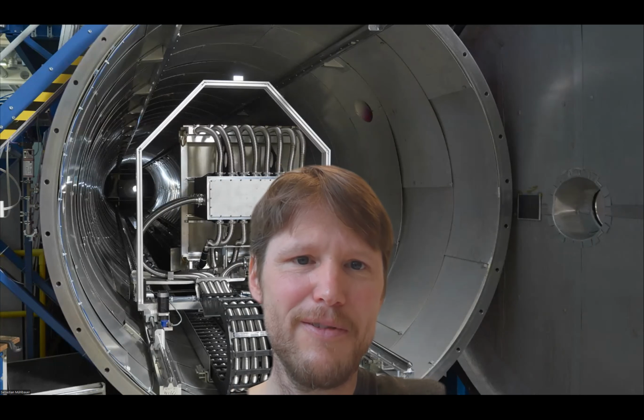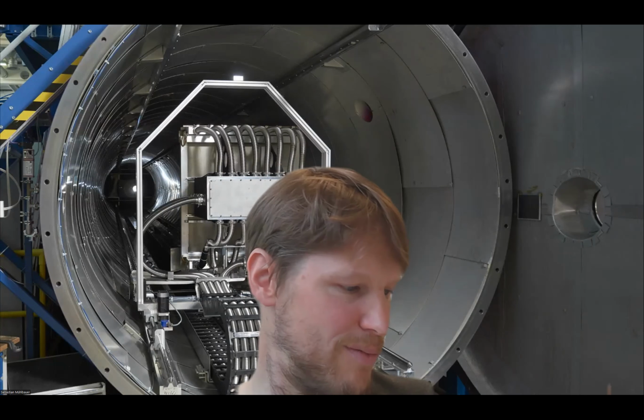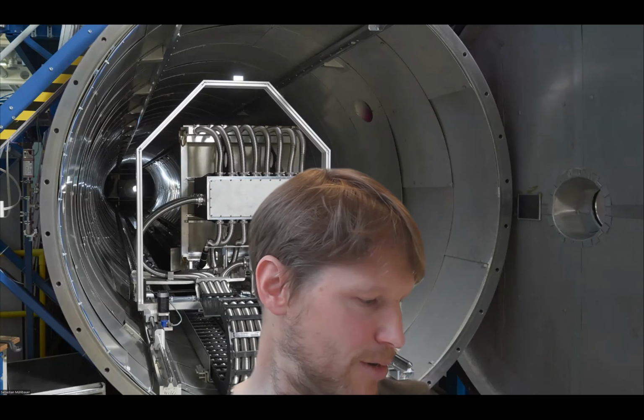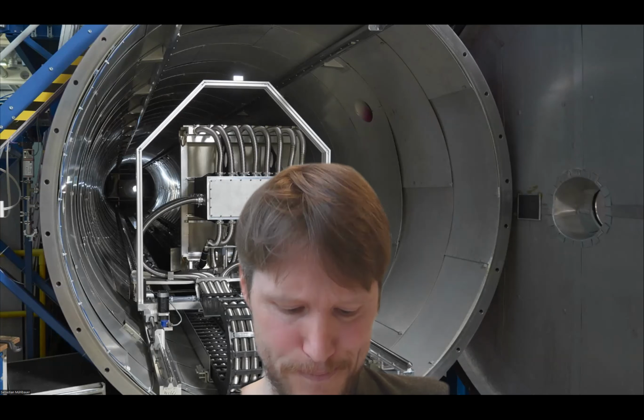And so the fluctuations do have a finite energy. Finite energy widths, and I was wondering if your Pauli paramagnetic scattering would be possible to measure the line widths of, because in principle it should not be static, it should be fluctuating. I bet you would need a very, very good energy resolution to look at this, but it might be impossible to do just because of the width of the energy. But I think why not think about whether this would be possible to do that.